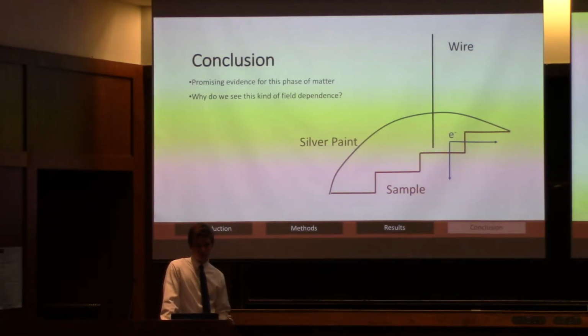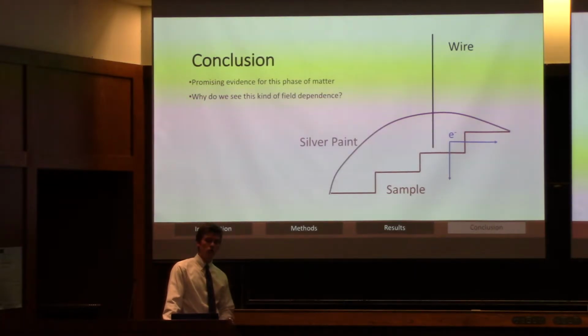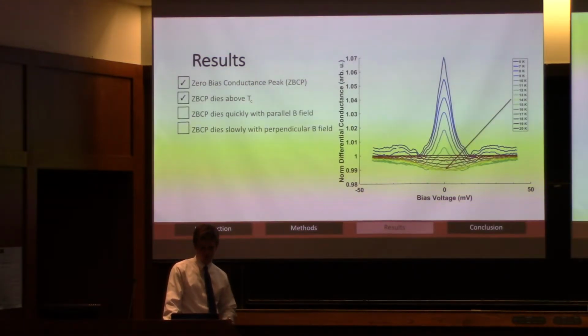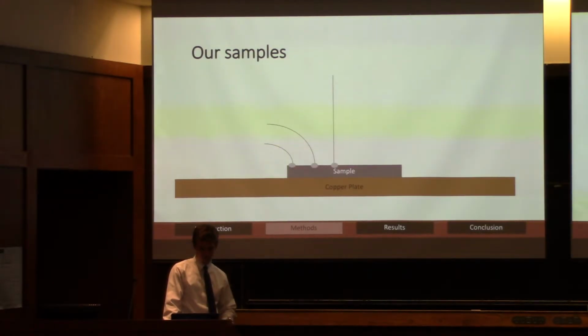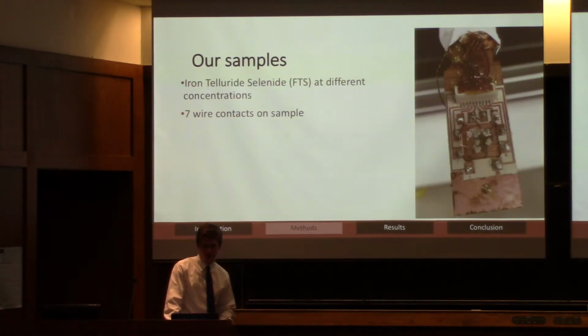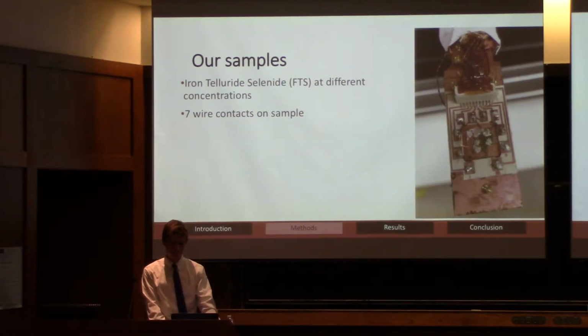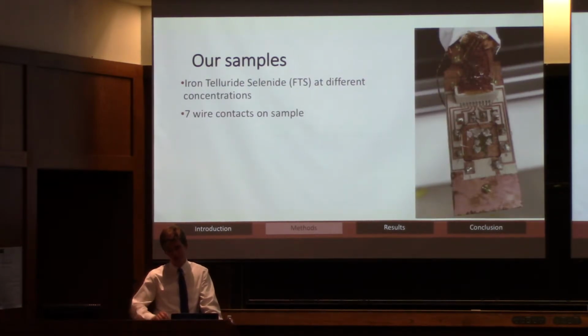So is this focused on a molecular level? Larger than molecular, but very, very small. So the sample itself, this sample right here, is probably about 0.1 millimeter thick, maybe. I have some AFM of it that shows that it's not perfectly smooth, but it'd be quite difficult to get it so smooth and get contacts that are so good that you don't actually have access to different levels of it. But that's definitely something that needs to be looked at moving forward.